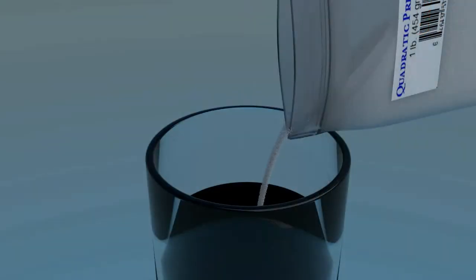Now, add 1 ounce or 2 level tablespoons of quadratic precipitant for every ounce of dissolved metal. Quadratic precipitant is what is called a selective precipitant. It converts just the gold back into particle form. All other metals will remain dissolved.